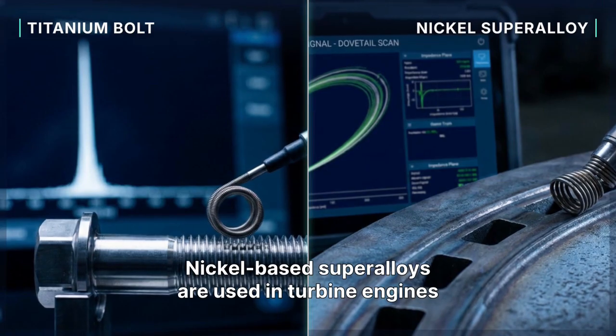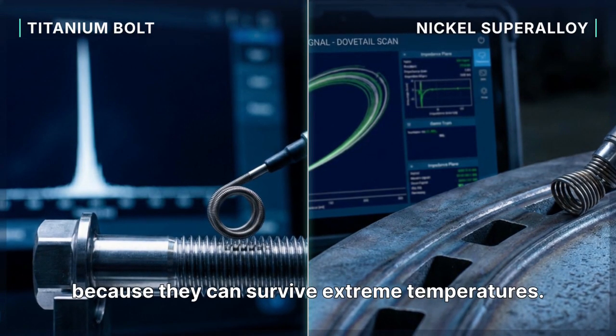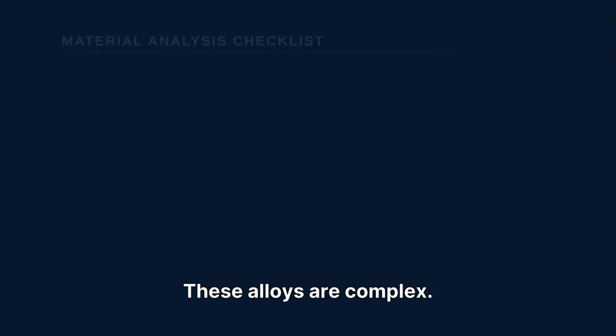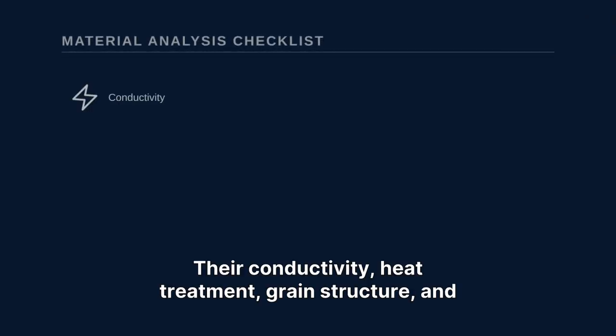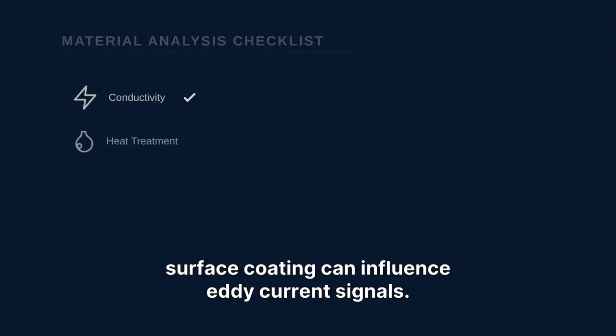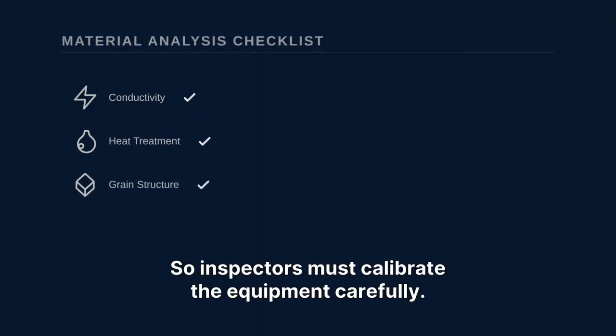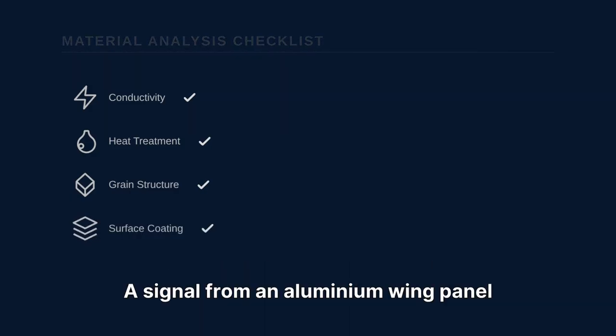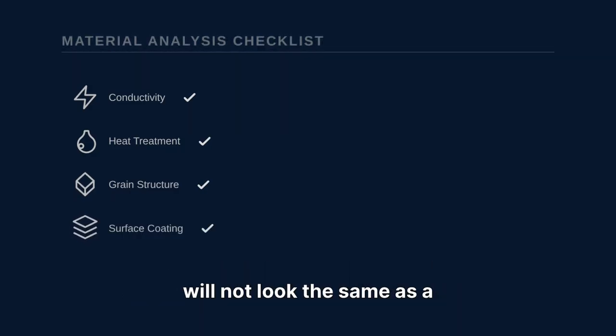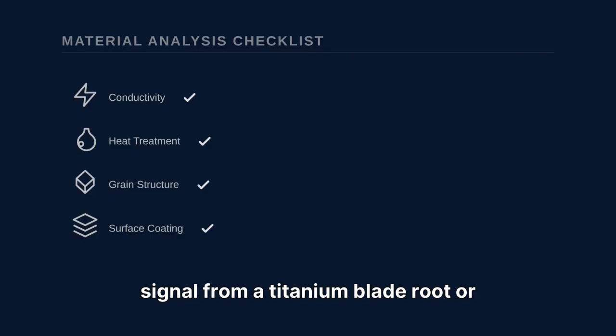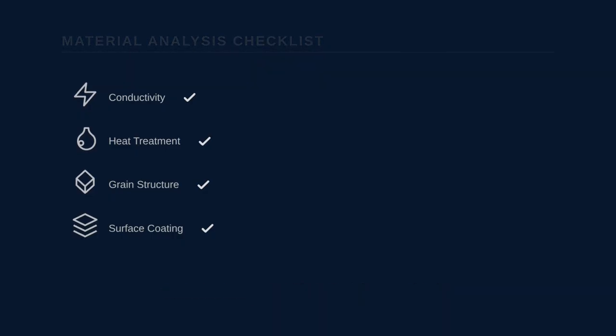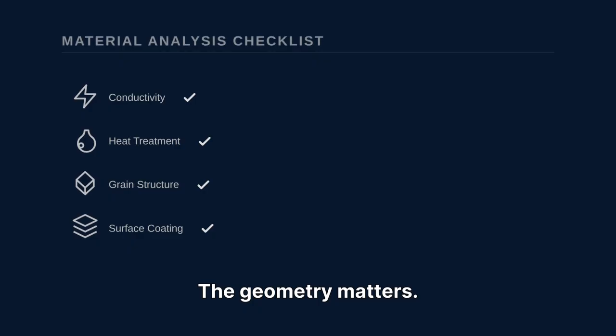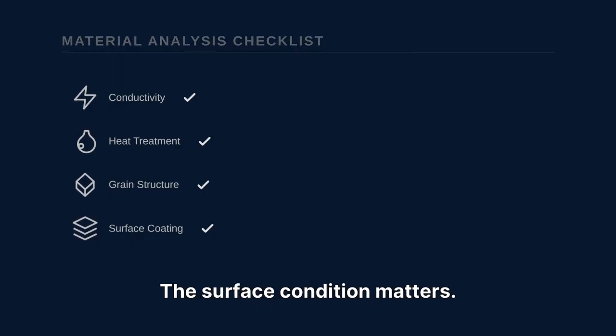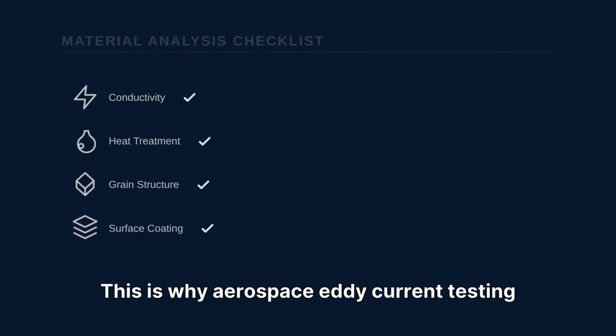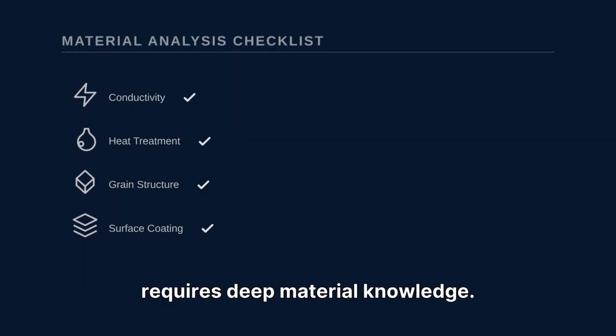Nickel-based superalloys are used in turbine engines because they can survive extreme temperatures. These alloys are complex. Their conductivity, heat treatment, grain structure, and surface coating can influence eddy current signals, so inspectors must calibrate the equipment carefully. A signal from an aluminum wing panel will not look the same as a signal from a titanium blade root or nickel superalloy turbine disc. The material matters, the geometry matters, the heat treatment matters, the surface condition matters. This is why aerospace eddy current testing requires deep material knowledge.